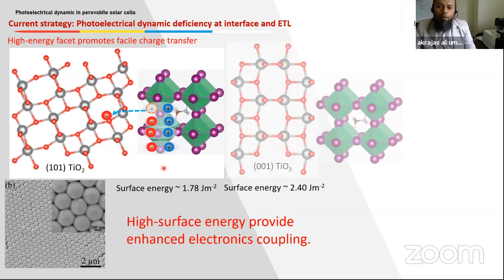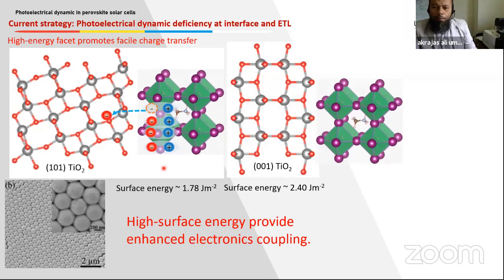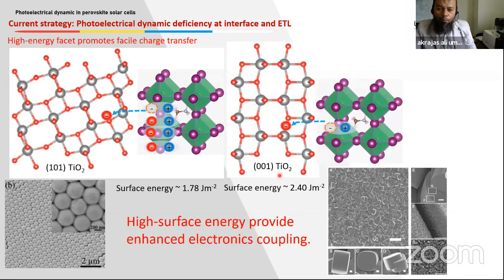So if we prepare TiO2 with a high-energy facet, for example here 001, which is much higher in surface energy, we expect better electron coupling between perovskite and TiO2, then we may have a better charge transfer process. This is a typical example of a 001 faceted TiO2 thin film.